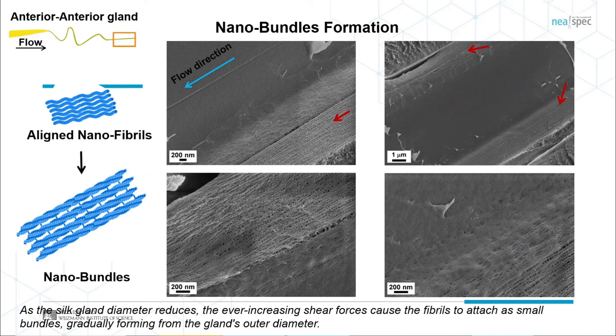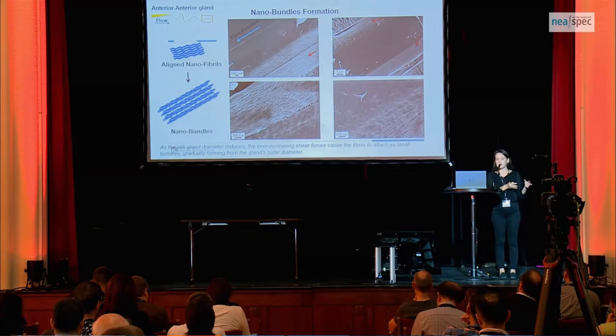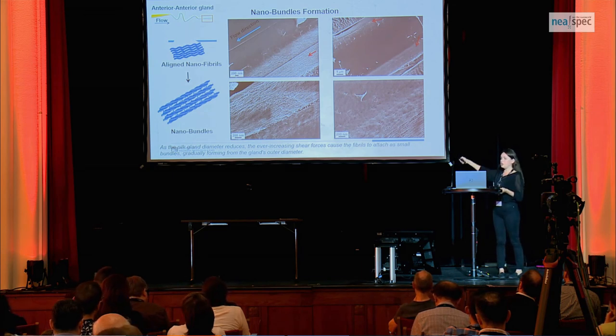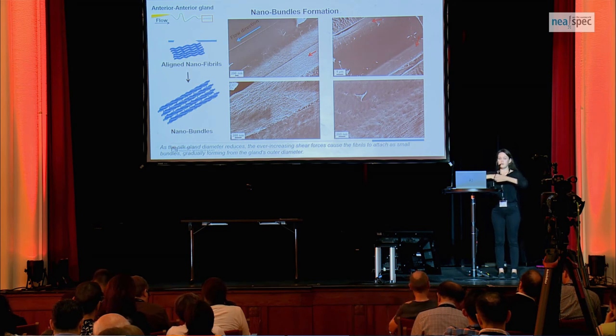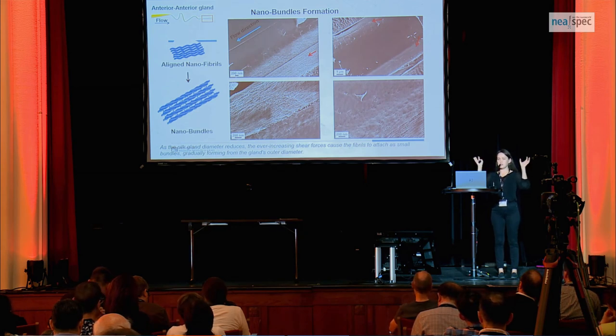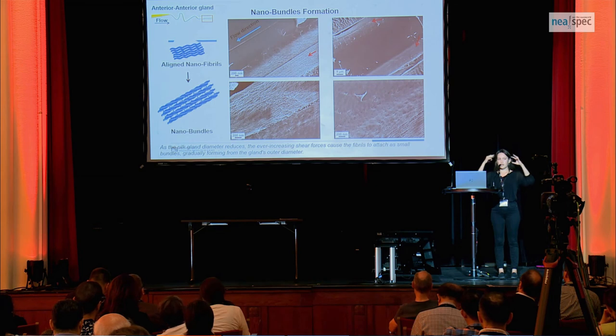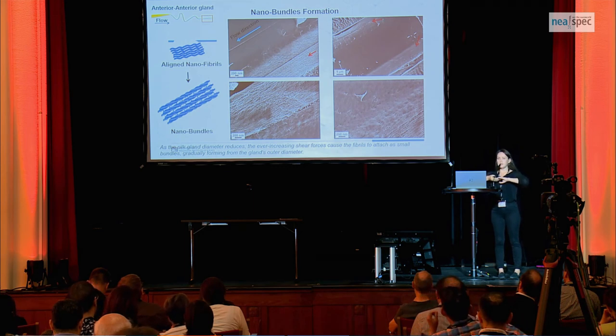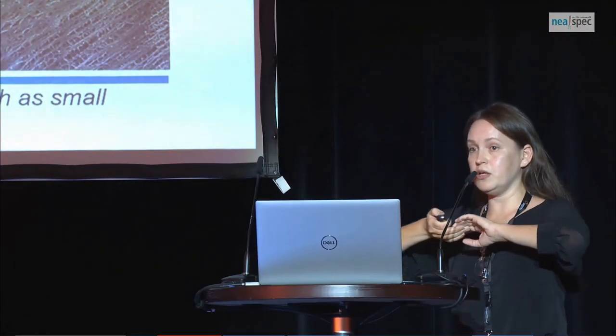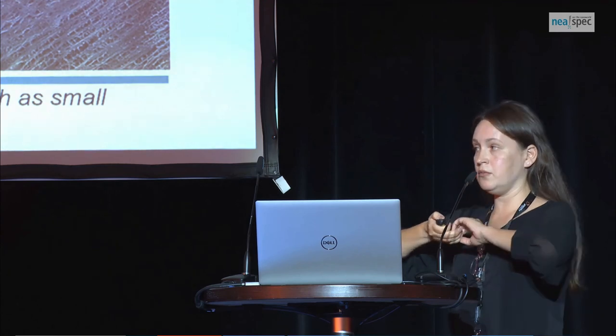The aligned liquid then transforms into aligned nanofibrils, where the structural transition from random coil to beta-sheet-rich structure occurs, and aligned fibrils form cross-links between them, making the silk fiber strong. Comparing the natural system with artificial reconstituted silk fibroin, this step is fundamentally different because reconstituted silk fibroin first forms cross-links while lacking all protein subunits — the heavy chain and light chain linked by a single disulfide bridge, and the decorating P25 peptide important for cross-link formation and N-terminus to N-terminus dimerization.